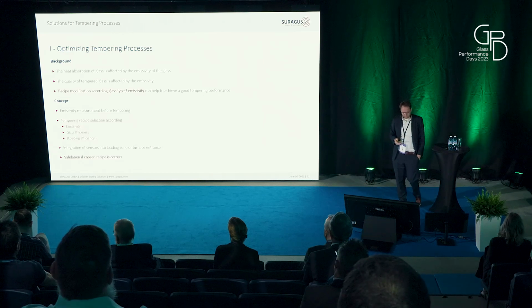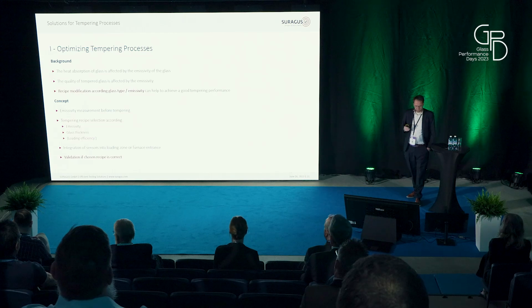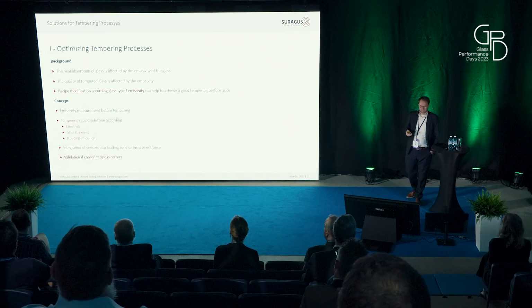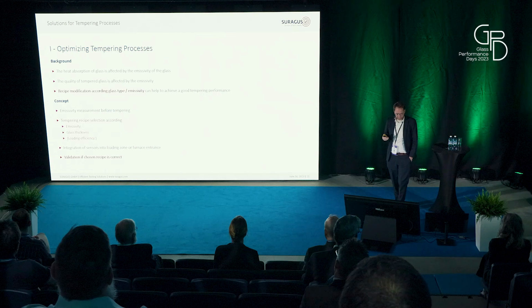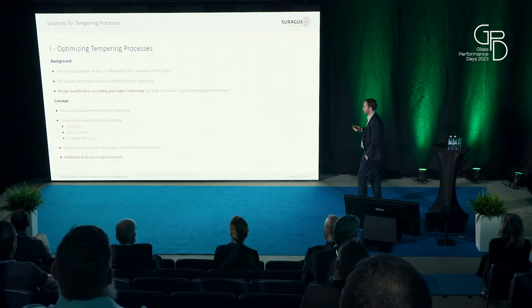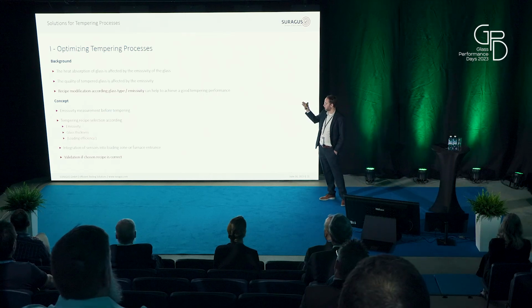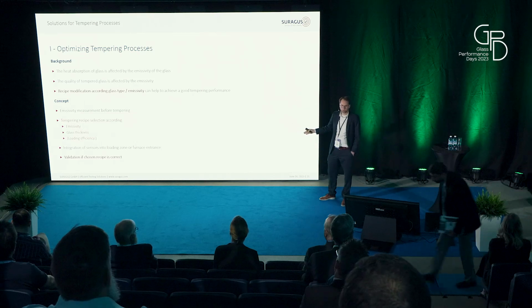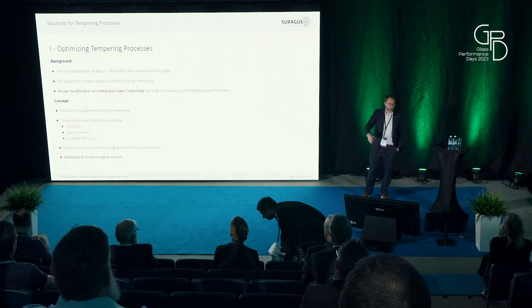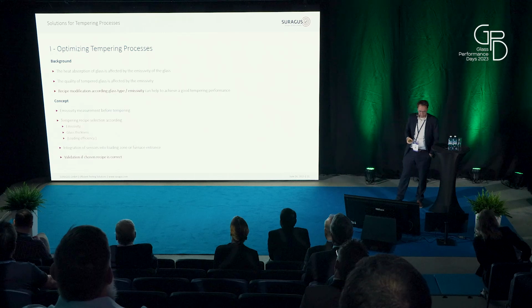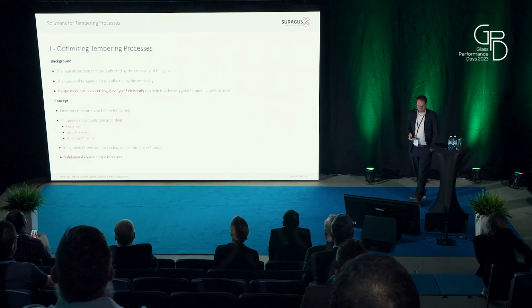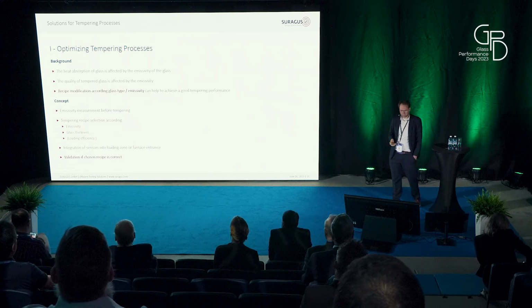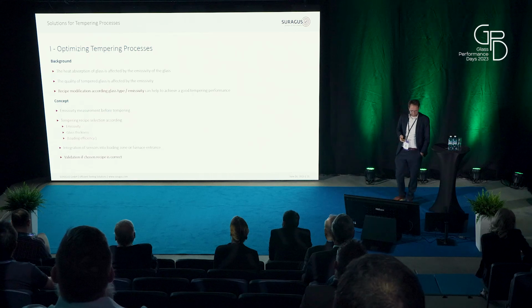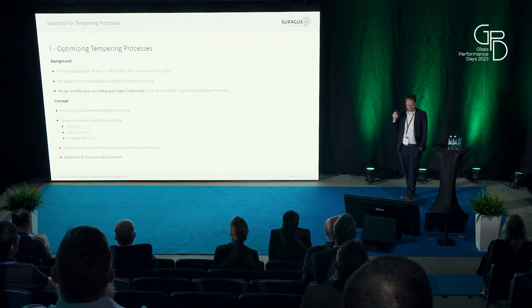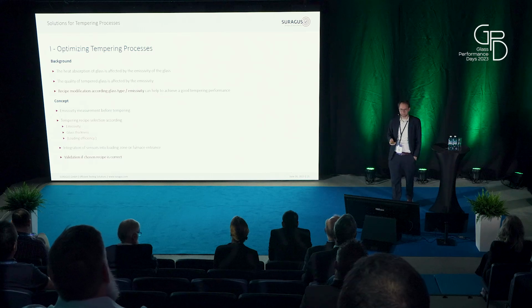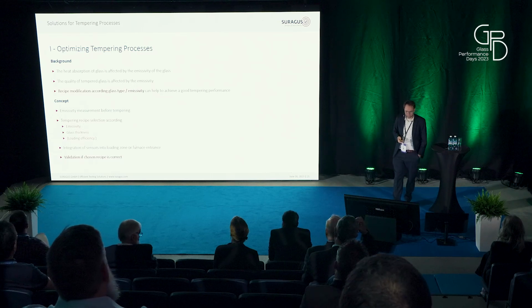The consideration of that can help to achieve a better tempering result. So the idea is to optimize the tempering effect. If you imagine that the emissivity is changing by up to 40% during the tempering, there's also a change during the process which can be considered. So the idea is to consider emissivity, glass thickness, loading, and many more things during the process, and feed this to the tool, or at least validate the recipes. This is the first step, to validate what you have on the table.